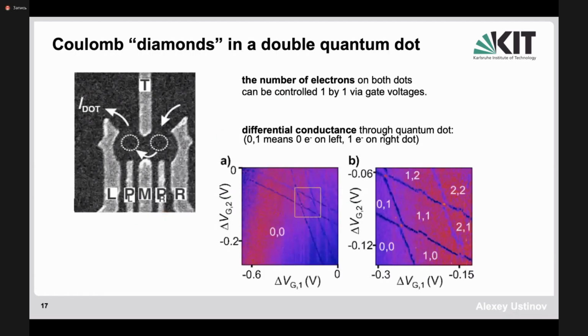So this leads to observation of the so-called diamond structures. And here on the diagram of the diamonds, you see, for example, if you zoom, this is the differential conductance, okay? The dark area is where the current appears, and the red area is where no current takes place. And you see there is a large area where there were no electrons in the dot. This is this whole space to the left and to the down direction of this plot. But if you zoom here in this rectangle, then you see states in the double dot. This is a double dot because you have 2 of them.